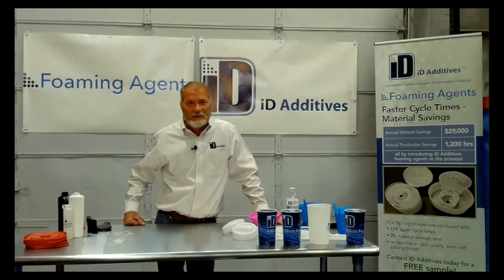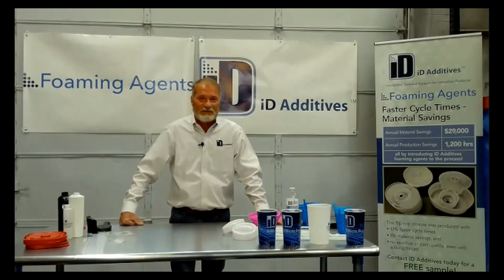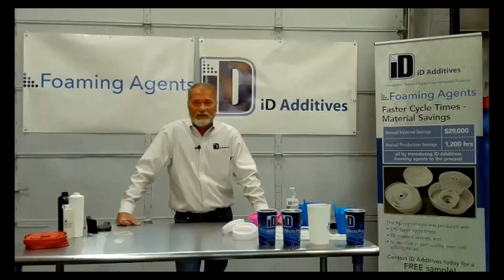Now then, if you want to really drop the weights, you inject it fast. The faster you inject it, the lighter it gets. If your fill time is a 3-second fill time, and you can get that down to 1, you're going to be super light.